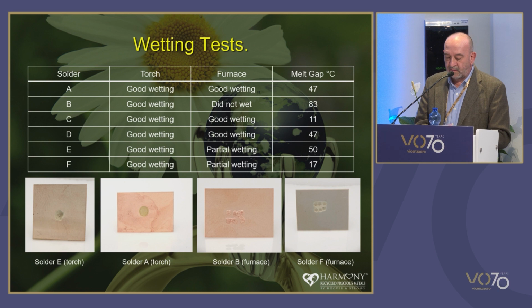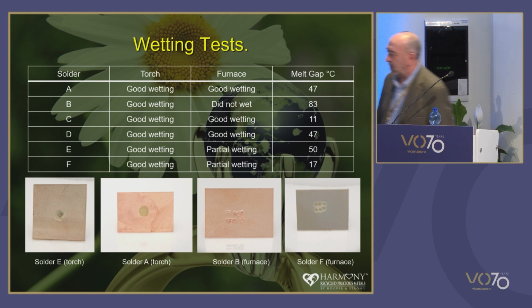Solder B in the furnace test was by far the worst result. There seems to have been some liquation of the pieces, but no discernible solder flow and no wetting on the sheet. I think that pointer, this is what I'm talking about.